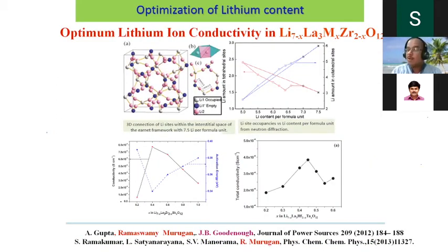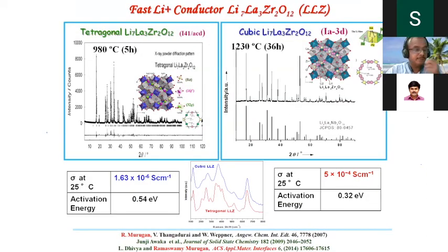Then I got interested in what the optimized concentration of lithium is, 6 or 7. Then we found that lithium 6.4 to 6.6 is the ideal composition to get the maximized lithium ion conductivity in these systems. But afterwards, I don't think you will be in a position to improve the conductivity. There's no meaning in working further.